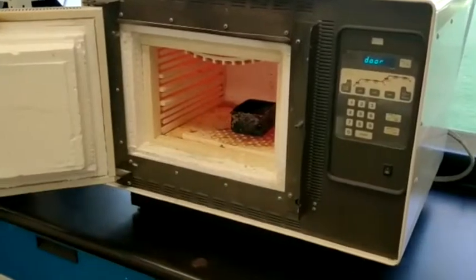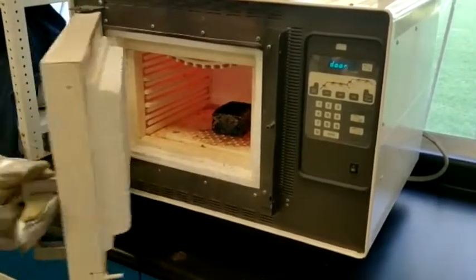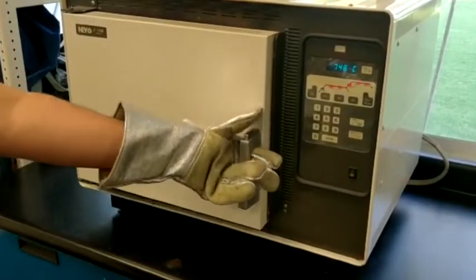After that, we took out just one piece and the other two, we put them into the oven at 800 Celsius degrees for 15 minutes. And finally, we put only just one piece in the oven at 200 Celsius degrees for 15 minutes. After that, we put them into bakelites in order to analyze them after doing the Vickers test.